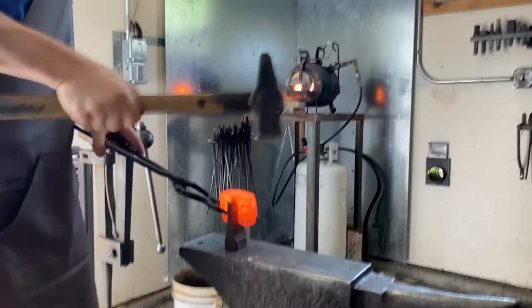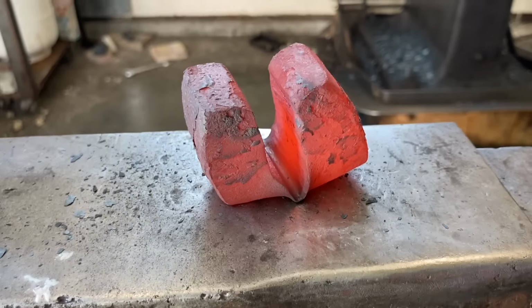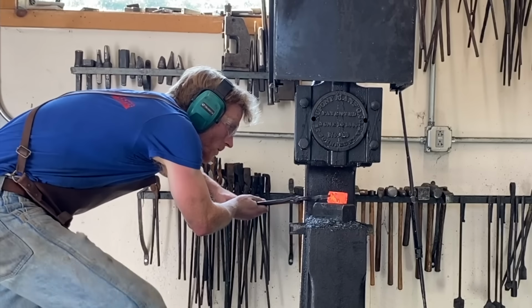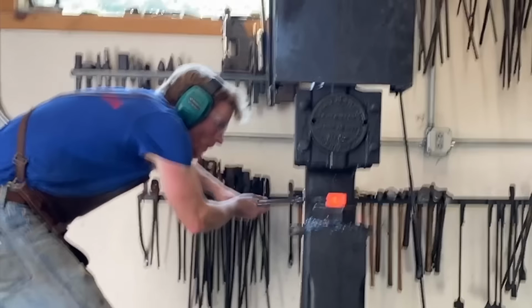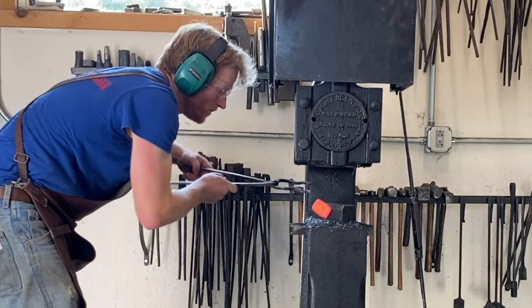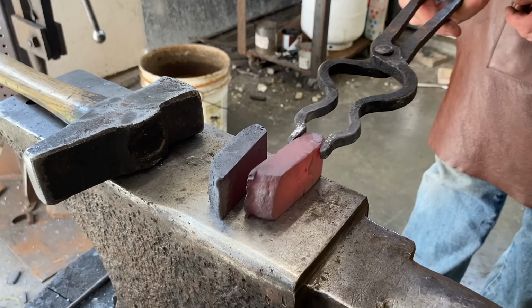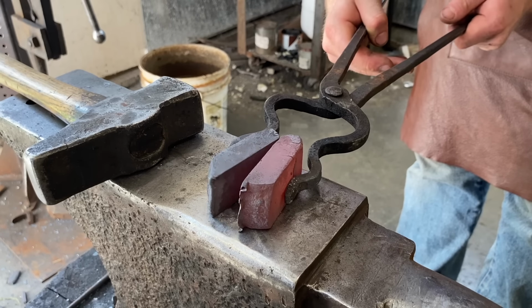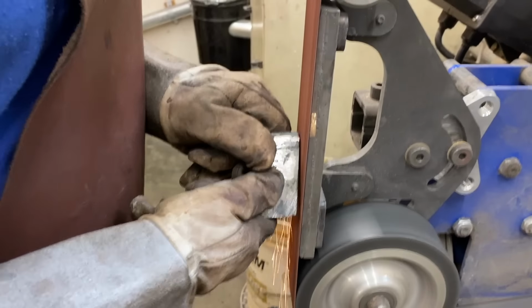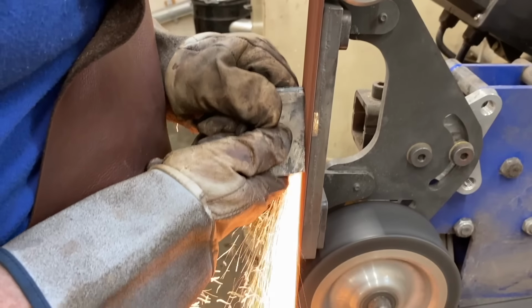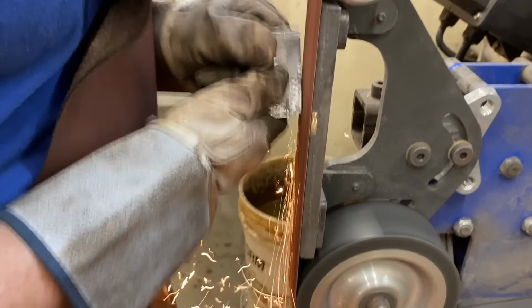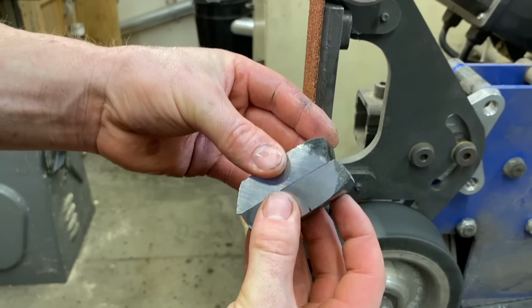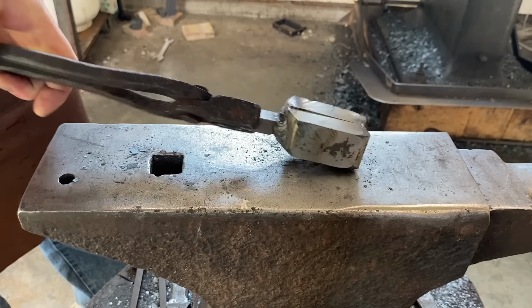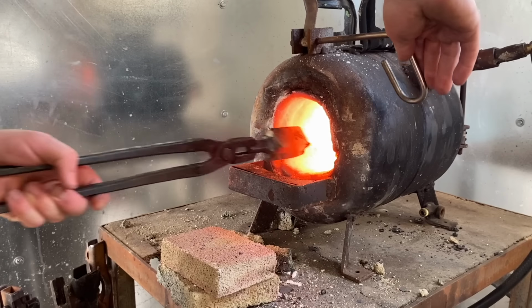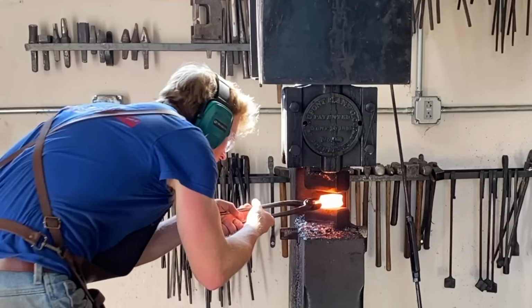If you look closely, you can see how the wedge drags the layers down in what will become the center of the feather. Then I re-squared and flattened both halves of the billet in preparation for welding them back together. Clean surfaces are paramount when forge welding, so I let these 2 halves cool and ground any forge scale off of the mating surfaces. Then I tacked them together again with a welder and put them in the forge for the final welding heat.